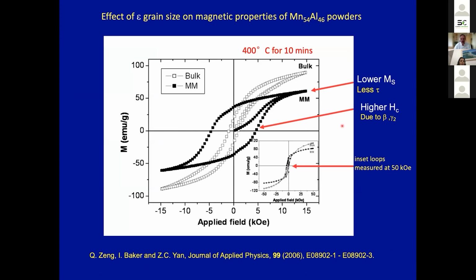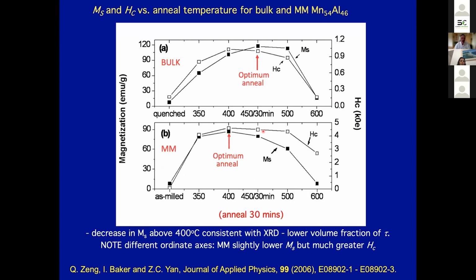This shows the results for two materials, a bulk material and the mechanically milled material, annealed at their optimum annealing conditions. And you can see the effect of mechanical milling is actually to reduce the saturation magnetization, but it significantly increases the coercivity in the material. And that coercivity increase is probably not due to fine grain size. It's probably due to the fact that you've got these beta and gamma 2 precipitates that are pinning the domain walls.